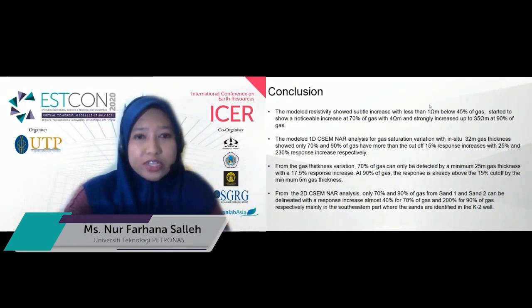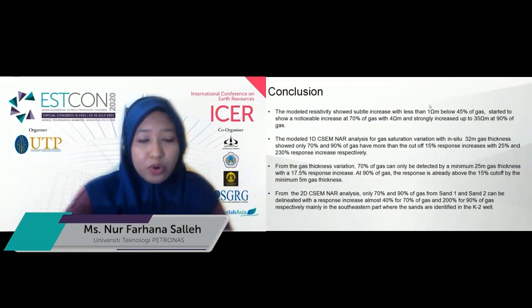From our model resistivity, the resistivity increased very slightly, with less than 1 ohmmeter below 45% of gas. We start to notice the resistivity increase at 70% of gas, around 4 ohmmeter, and it strongly increases up to 35 ohmmeter for 90% of gas. From our 1D model CSEM with gas saturation variations, only 70 and 90% of gas show more than the cutoff response, with 25% for 70% of gas and 230% increase for 90% of gas.